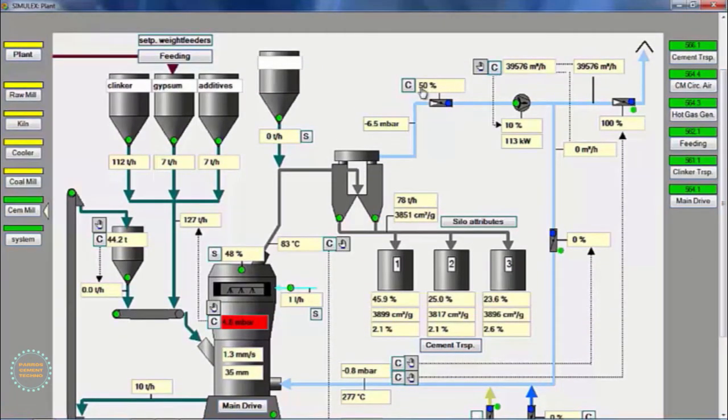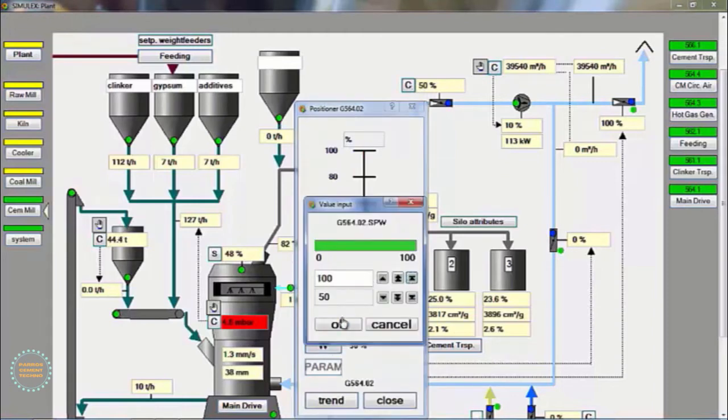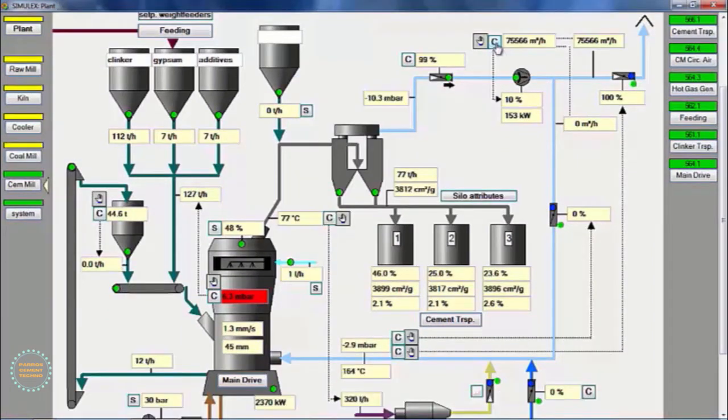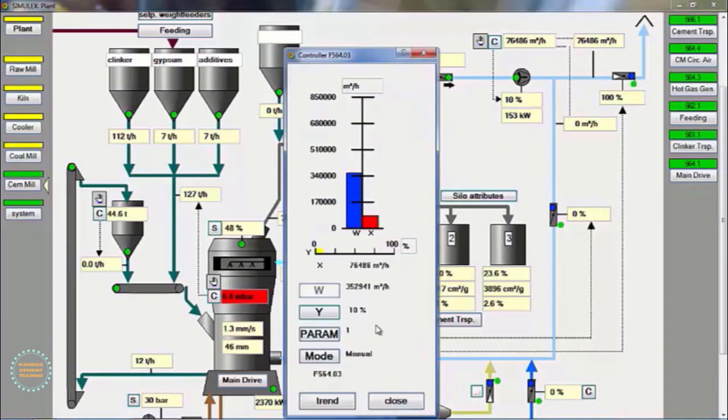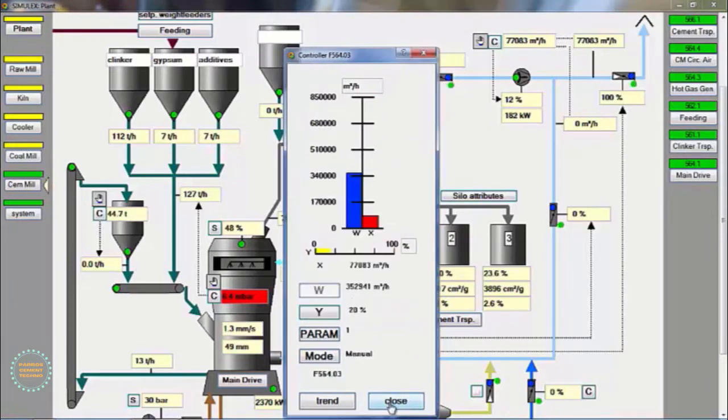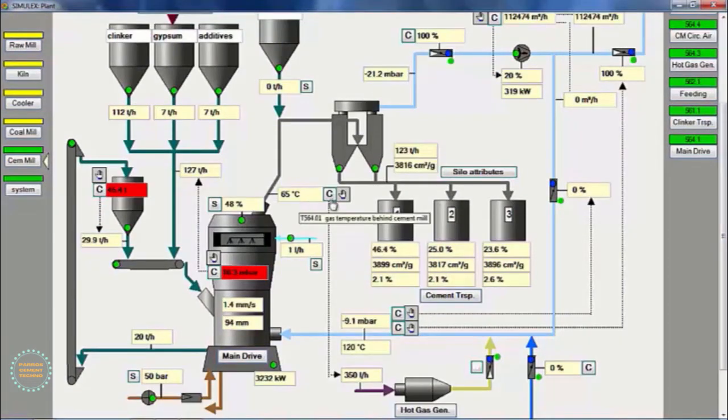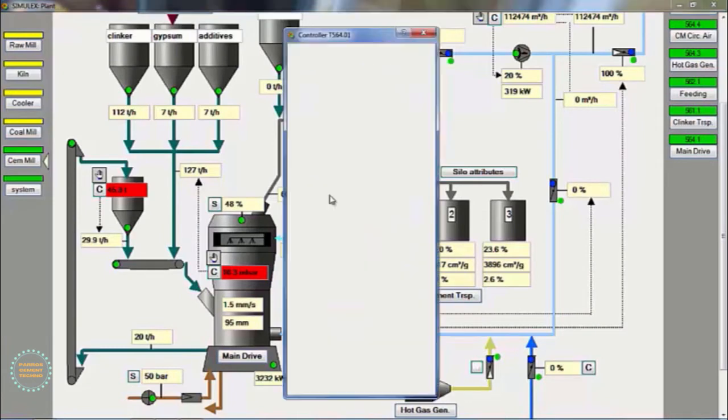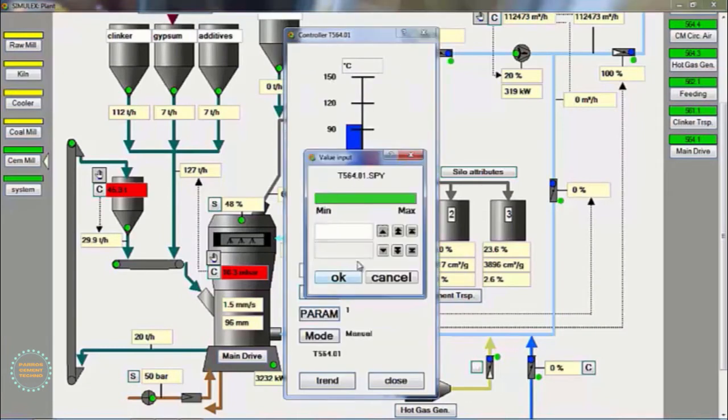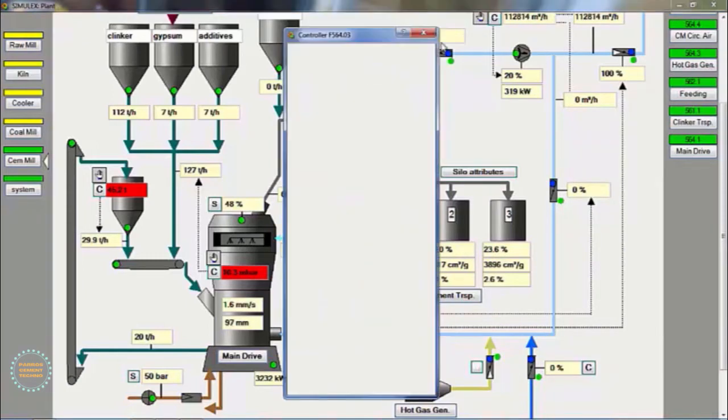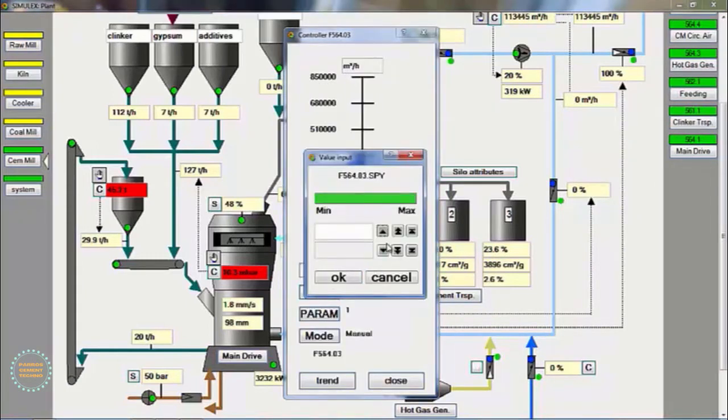Increase hydraulic pressure gradually by observing changes in bed material and mill vibration. Next, open the 100% mill ID fan damper, and increase the mill ID fan speed gradually, according to the operating conditions in the mill. This is when the mill outlet temperature drops, so we increase the fuel consumption from 350 to 400 liters per hour, and increase the mill ID fan speed, then we observe changes in the operating parameters.